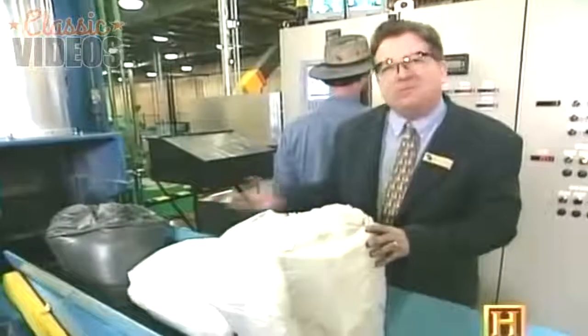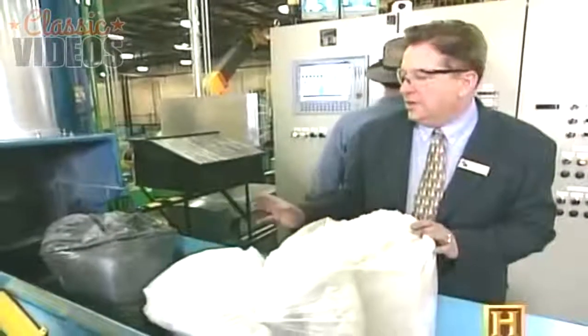We've taken the materials that we just described, and we're actually going to use a technique called upside down mixing, where we're going to load the carbon black, the balance of the fillers and plasticizer, and then load the polymer, the raw synthetic EPDM, last. Lower the ram, masticate, put this together, and then based on temperature, we will add the curative to the mix to get a homogeneous mix.